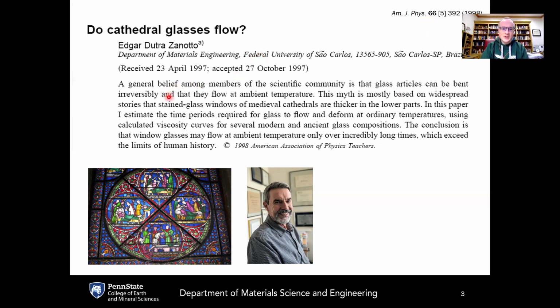He says, a general belief among members of the scientific community is that glass articles can be bent irreversibly and that they flow at ambient temperature. This myth is mostly based on widespread stories that stained glass windows of medieval cathedrals are thicker in the lower parts. In this paper, he estimates the time periods required for glass to flow and to deform at ordinary temperatures using calculated viscosity curves for several modern and ancient glass compositions. The conclusion is that window glasses may flow at ambient temperature only over incredibly long times, which exceed the limits of human history. So what Professor Zanotto did was he considered several different types of glasses, and the key property that we need to evaluate whether a glass is flowing or not is the viscosity.